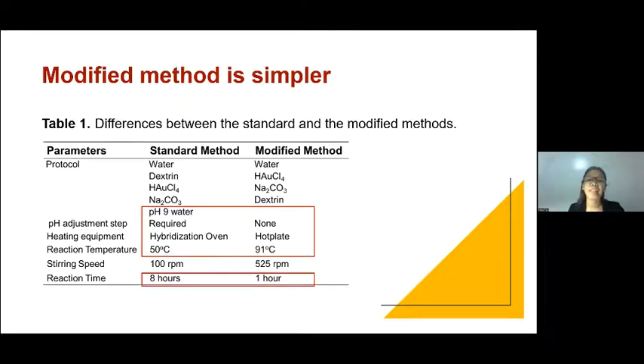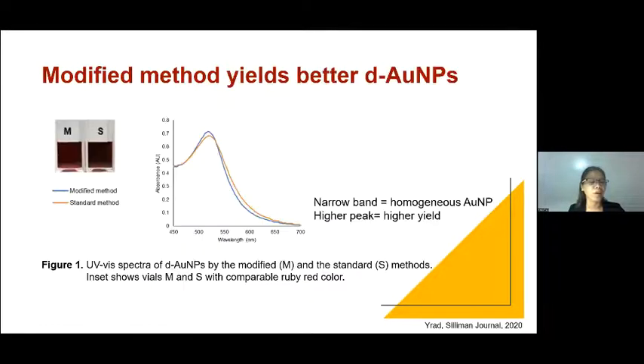The differences between the standard and the modified methods are presented in the table. The key features in the modified method are the reversal of the addition of the reagents and the increase in the reaction temperature. Modification of the method makes the synthesis simpler, with accompanying plus factors, such that the need for the pH water, pH meter, and steps were no longer needed. The hybridization oven was replaced with a less expensive hot plate, and most of all, the reaction is reduced from 8 long hours to 1 hour.